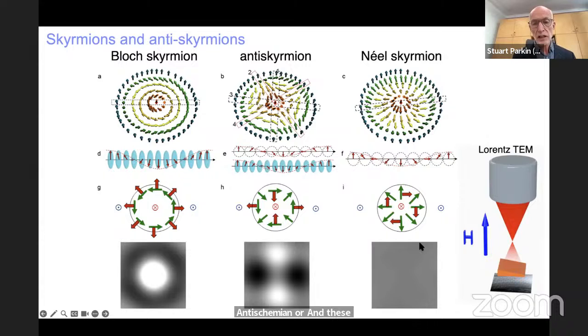These are actually calculations by Changping Ma, who was a PhD student and then postdoc. Now he's back in China. He first used micromagnetic simulations to calculate these spin textures, and then used standard transport intensity equations to derive these Lorentz forces and therefore the image in the imaging plane of the microscope. What's interesting is that the Bloch skyrmion looks like a single bubble of increased intensity of the electron beam, whereas in the Néel skyrmion, the deflection of the electron beam is around the circumference of the object, so that you see nothing in plain view. If you tilt the object in the Néel case, you can actually see something. I'm going to come back to that later.